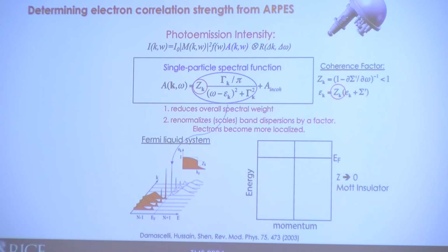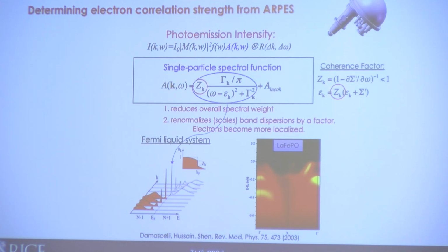Right. So practically, what we do, we take a new material and we measure the band dispersions. For example, this is one of the first iron pnictide superconductors, and you will see these spectra here, and you can sort of make them out. And then you just slap on the DFT calculations, and for moderately correlated materials, you will realize that you can make some reasonable agreement between the measured dispersions and the DFT calculations if you renormalize or squeeze the DFT bands by a certain factor, and this factor is a quantitative measurement of this coherence factor. It's 1 over the coherence factor. So this is a direct way that we can utilize to compare the correlation strength across different materials. This is just a visual way of seeing what we actually measure.